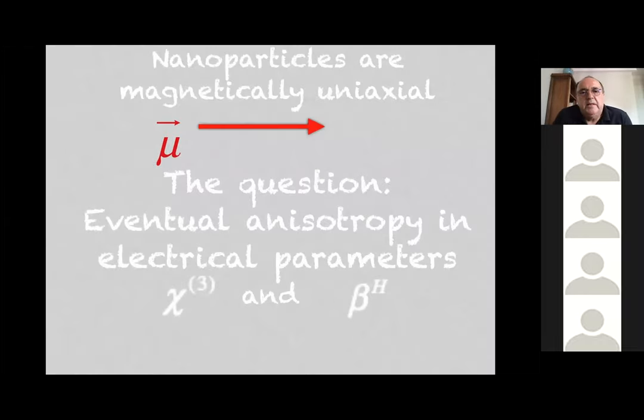Well, basically, if you have a ferrofluid with nanoparticles, typical size of about 10 nanometers, without the magnetic field, it is an isotropic fluid. When you put an external magnetic field in this material, it becomes anisotropic from the point of view of magnetism, because we will align basically the magnetic moments of the particles, so we have a uniaxial anisotropy of this fluid in the presence of the magnetic field.